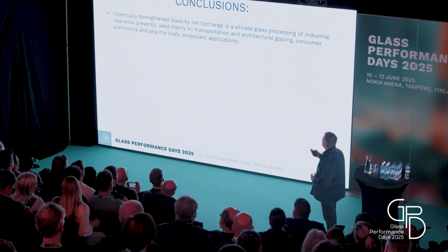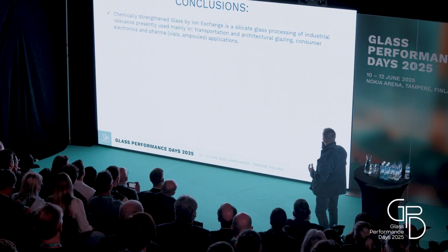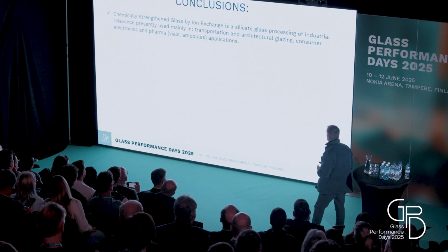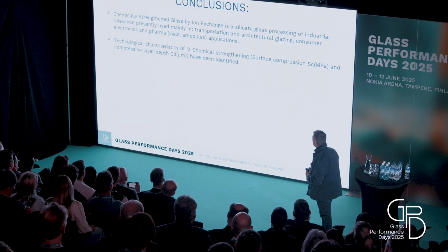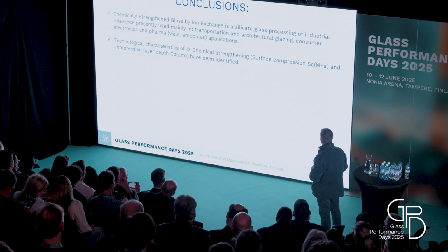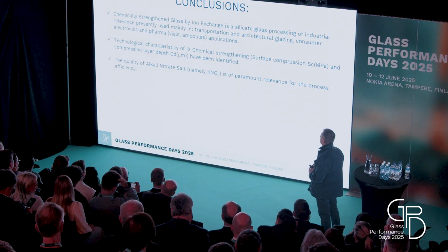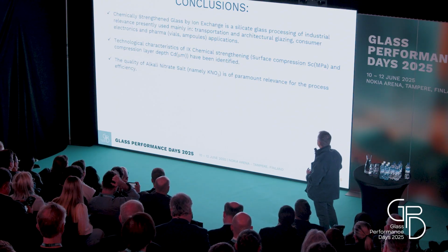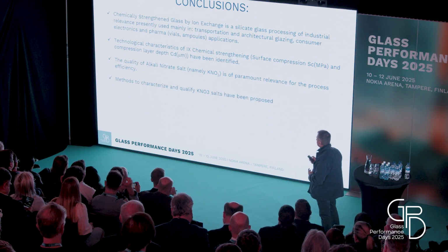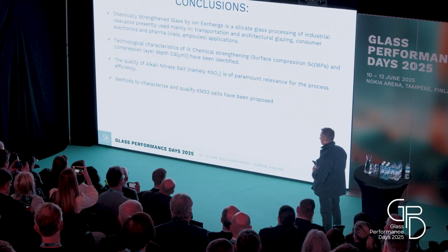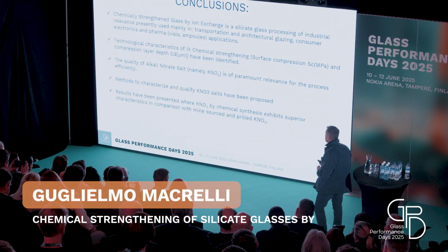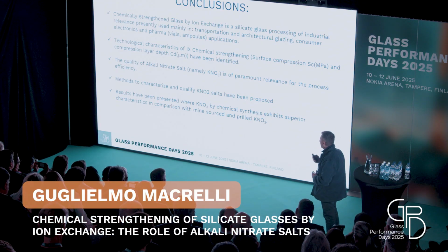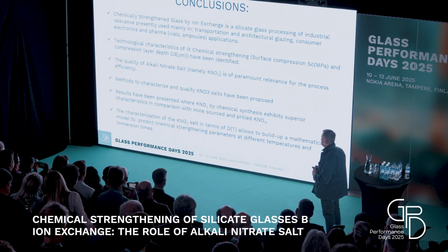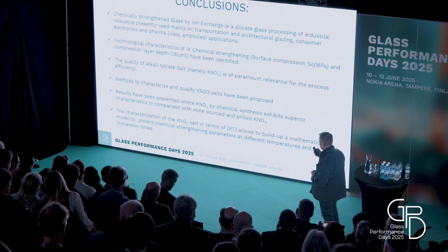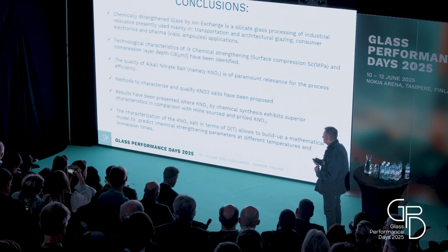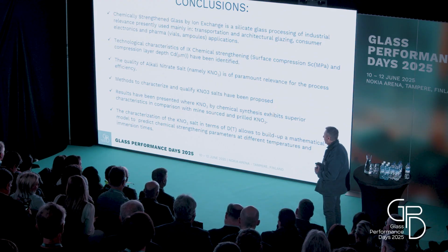Conclusions. Chemical strengthening of glass by ion exchange is a silicate glass process of industrial relevance. It is used mainly in transportation, architectural glazing, consumer electronics, and pharma. Technological characteristics of ion exchange, surface compression and compression layer depth, have been identified. The quality of alkali nitrate salt, namely potassium nitrate, is of paramount relevance for the process efficiency, and methods to characterize and qualify potassium nitrate salt have been proposed. Results have been presented where potassium nitrate by chemical synthesis exhibits superior characteristics in comparison with mine-sourced and prilled potassium nitrate. And the characterization of a potassium nitrate salt in terms of D versus temperature allows building a mathematical model to predict chemical strengthening parameters at different temperatures and immersion times.